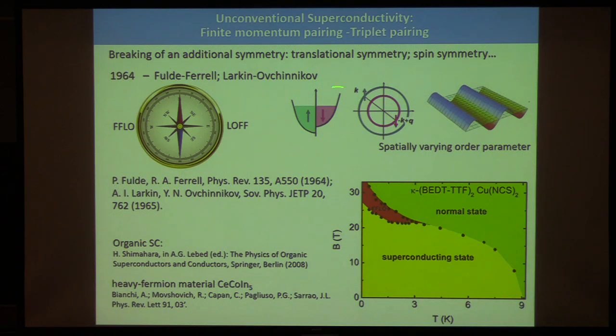And the phase basically addresses the following very simple system. So imagine an itinerant ferromagnet where I have a little bit more spin-ups than spin-downs. If one just looks at the Fermi surface of this material, one could see that the Fermi surface of the minority spins is small, and the Fermi surface of the majority spins is large. And you might ask, well, how can I now construct my singlet pairs? Remember, the construction before was to take opposite spins with precisely opposite momentum. Well, here, if I try to construct an opposite spin pair, you see that it will always have a momentum, regardless of how I choose it.